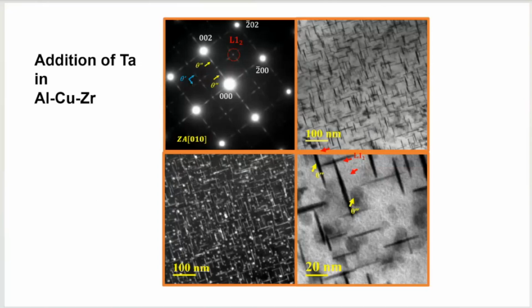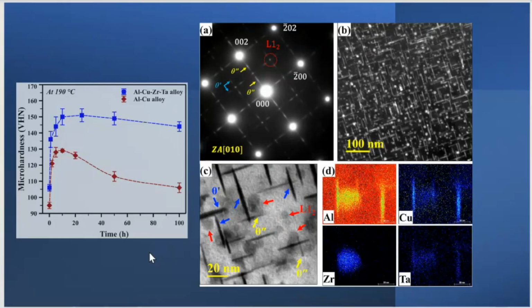And if you look at the microhardness to see both stability as well as the strength, it is a reflection of strength also. Then you can see the tantalum additions. The microhardness profile is very stable, and the microhardness VHN is quite high, 150 plus. And one interesting thing that you see is that zirconium is segregating only in the ordered precipitate, but tantalum is segregating both at the theta double prime and theta prime particles and their interface, as well as going to the ordered particles.